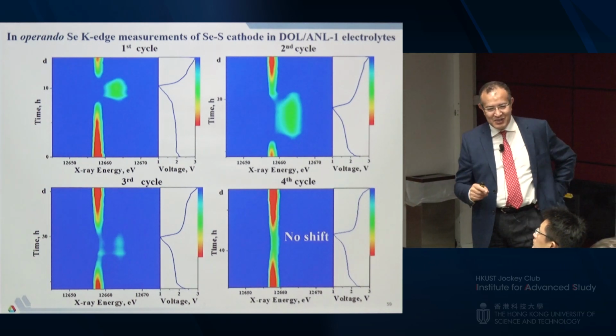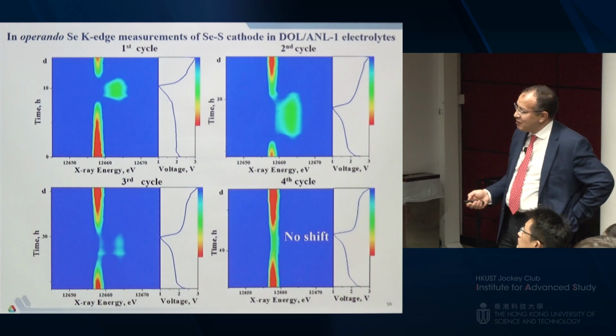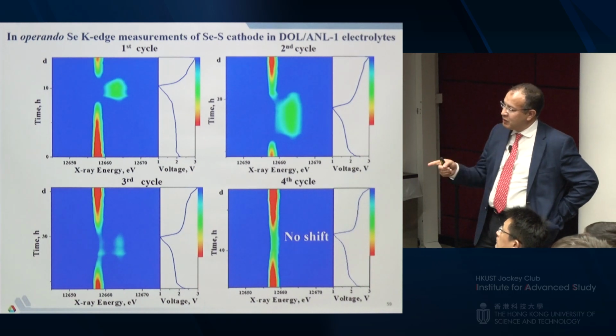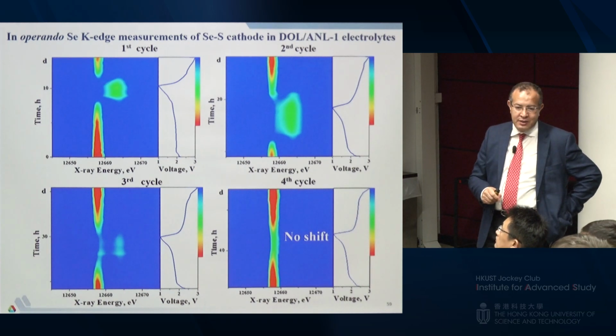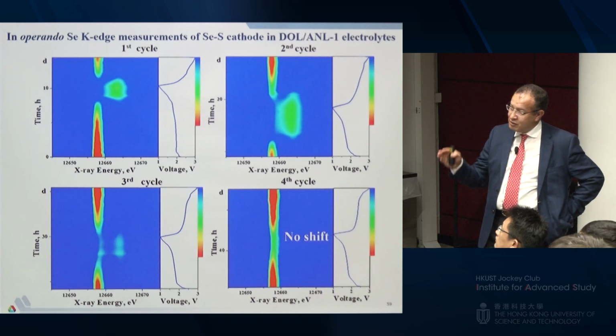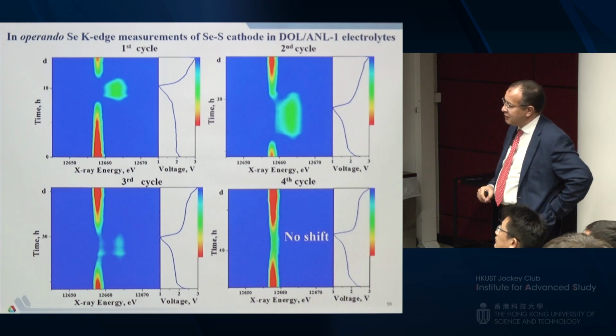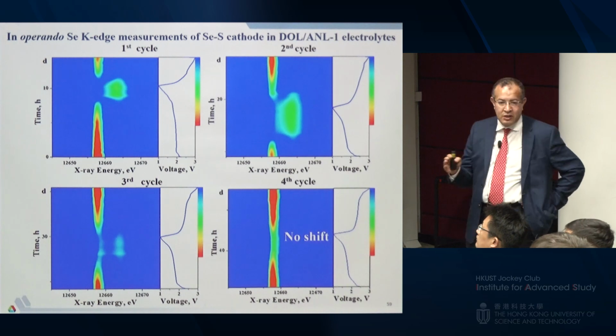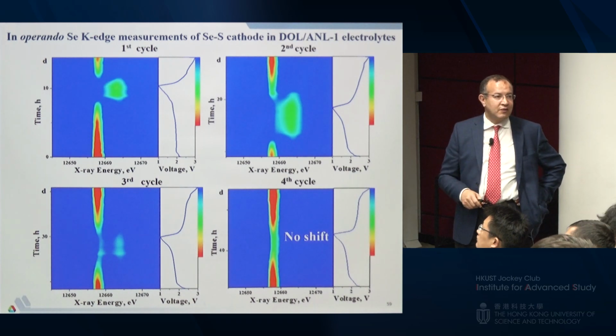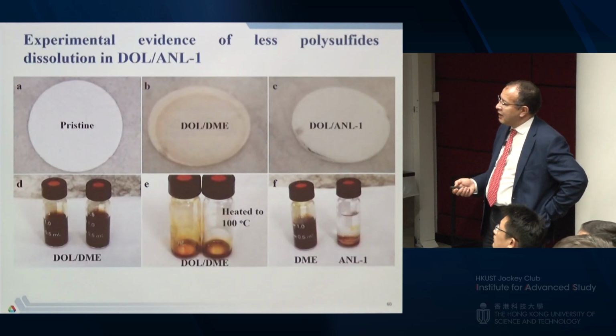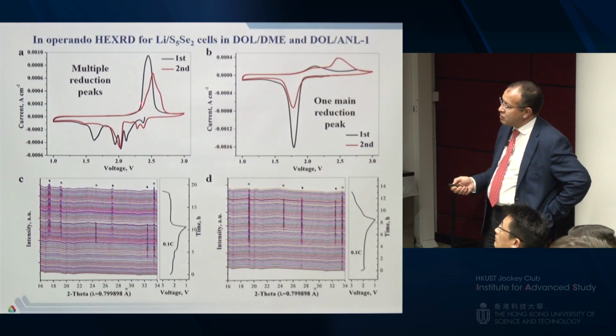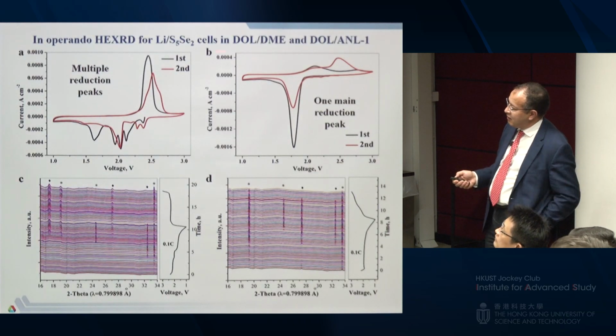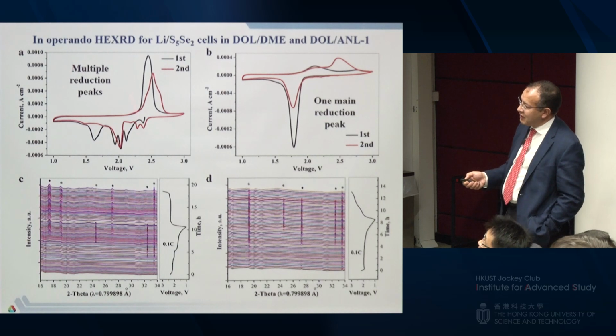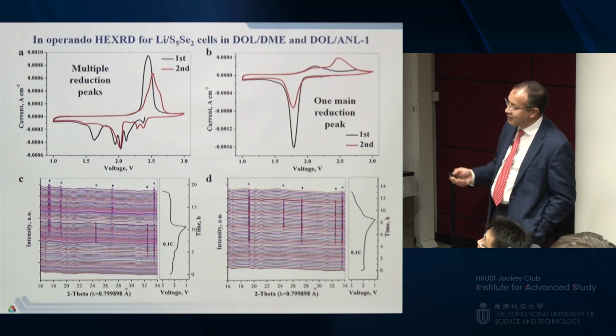You're not going to see it, because the color didn't change. It doesn't mean there is no dissolution. But here you are probing the liquid inside the cell while it is in operation, and you don't see any shift, which basically dictates there is no change in the oxidation state of these phases. And okay, we did this. Then you can see also when you run just a normal CV, this one has multiple phases. This one has a single phase, clearly.